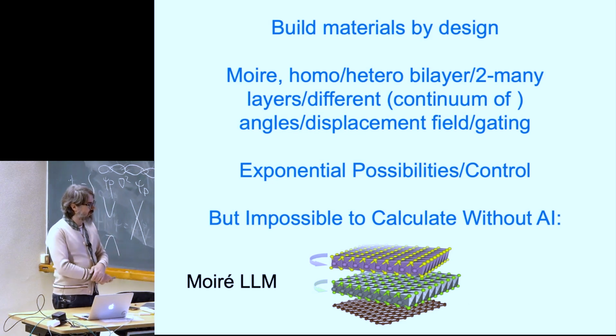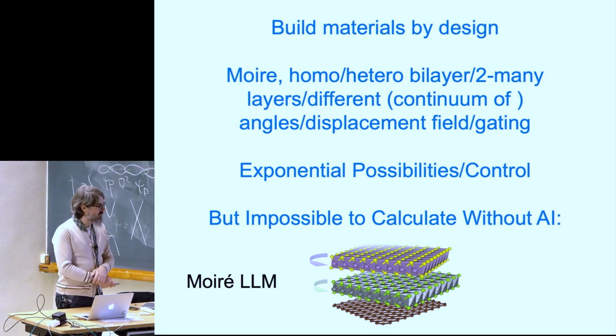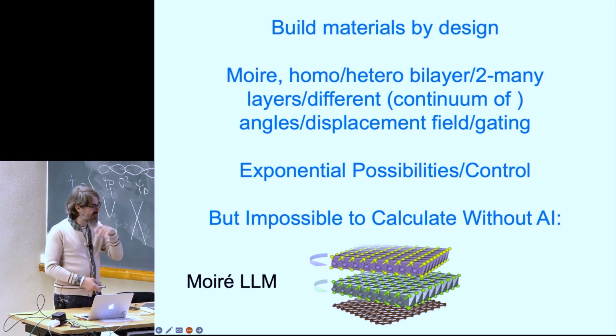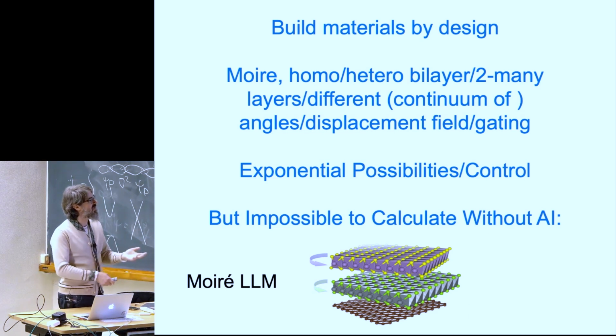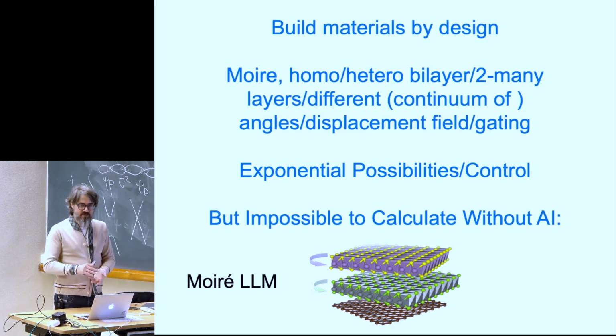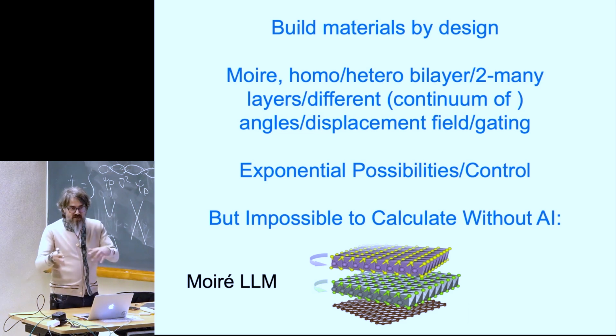But I also wanted to point out that there is a problem, and the problem is that there are at least 500 exfoliable materials, meaning either they have been exfoliated, which are around 200, or materials that exist in the bulk and are van der Waals, and those for sure will be able to be exfoliated. And then with 500 materials, you can put hetero and homo bilayers, you can put 2 layers, 3 layers, 4 layers, and then you can twist the angles of each one of these layers.